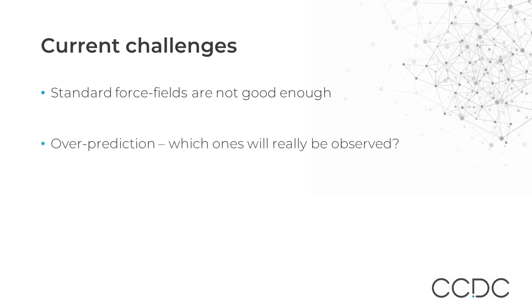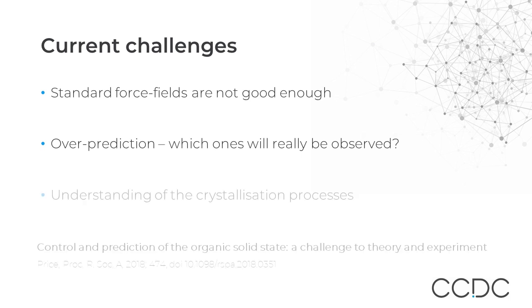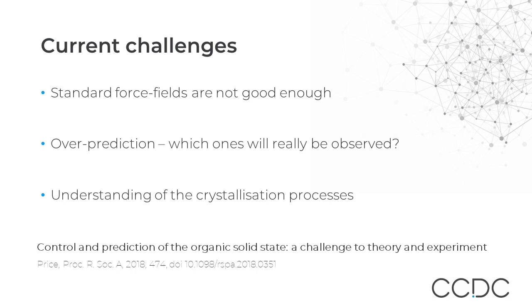There are many challenges in CSP that are still evident. The force fields and even the faster quantum mechanical methods are not adequate to rank crystal polymorphs. Progress requires the use of customized force fields for each family of problems and subsequent high-end re-ranking to make meaningful predictions. We have to accept that we generate large landscapes of structures, but many of these structures will simply never be observed — we over-predict. This confounds the use of CSP predictions as we cannot be certain if the structures we see could exist or are just artifacts of the computational method. Finally, to move forwards, we need a deeper understanding of the crystallization process. As Sally Price notes, we need to move from structural prediction to prediction of structure creation, which is entirely influenced by the experimental conditions.